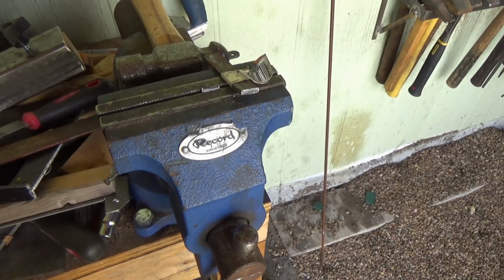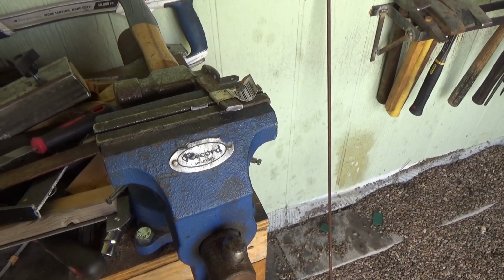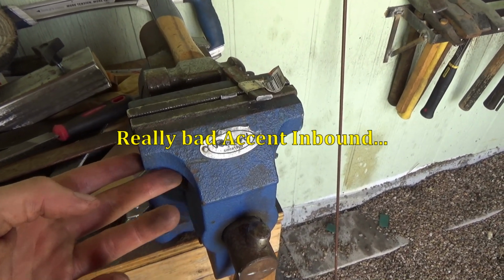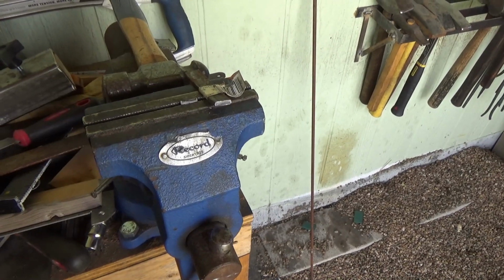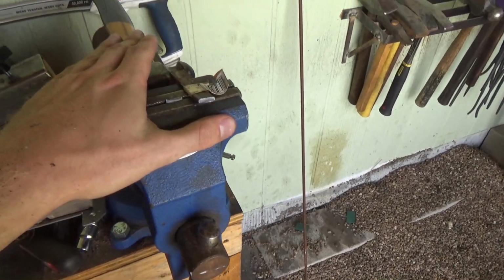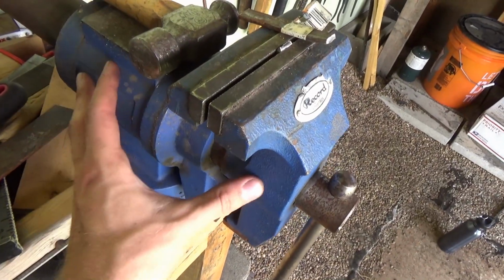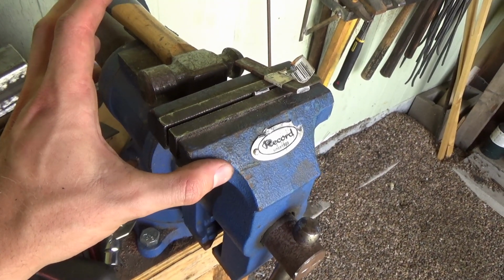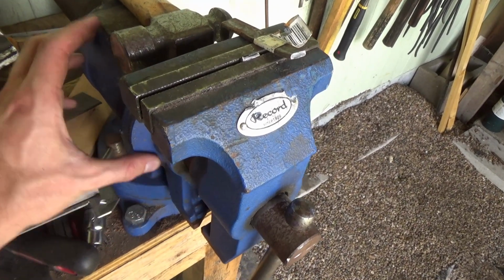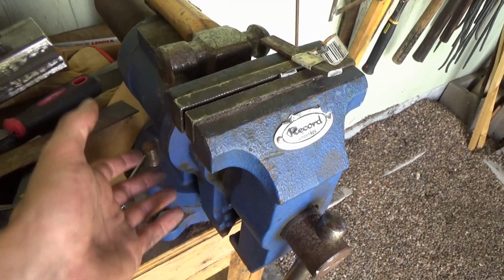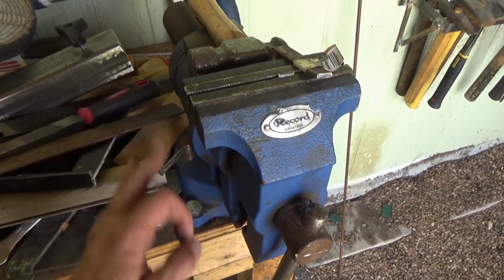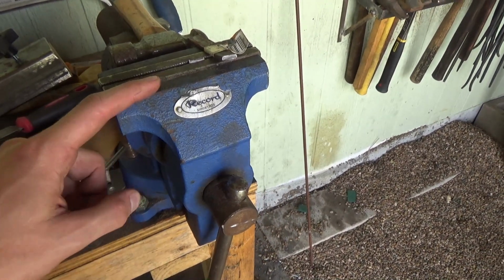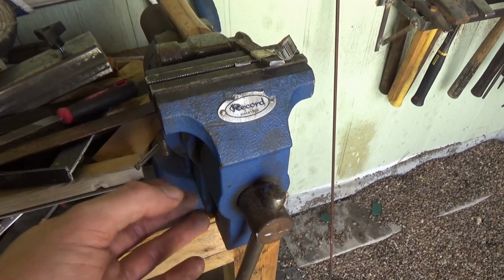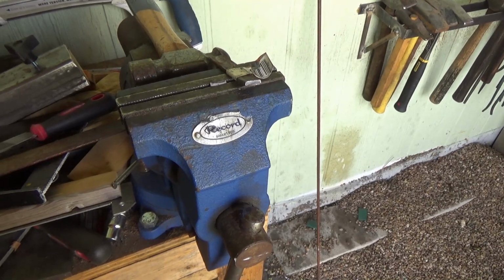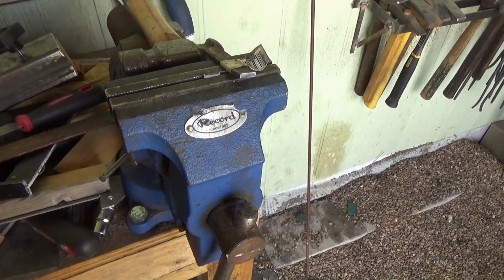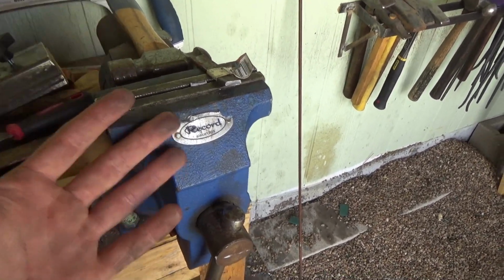If you want an example of that, go watch either Crushing an Anvil or Crushing a Vice by the Hydraulic Press channel. Okay? Go watch the hydraulic press crush a vice. The hydraulic press channel did a video where they crushed a cast iron vise. And it took stress, and then once it broke, the crack propagated from one side all the way to the other, and it shattered. Mild steel would not do that. Even a tool steel would not necessarily do that. Cast iron will. Ductile cast iron has those nodularizing elements in it, such as magnesium. Just a little bit of magnesium added to it, and suddenly it can be heat treated. It can be hardened. It can be tough and durable and used as a very effective anvil.